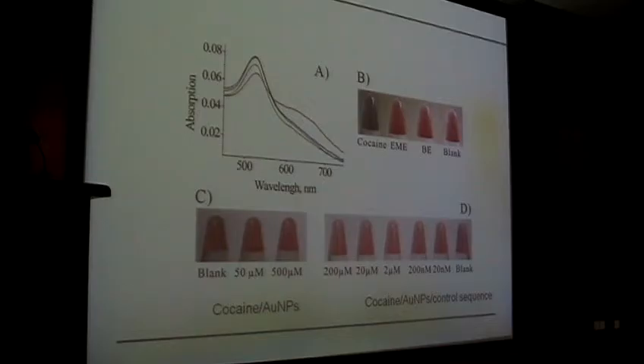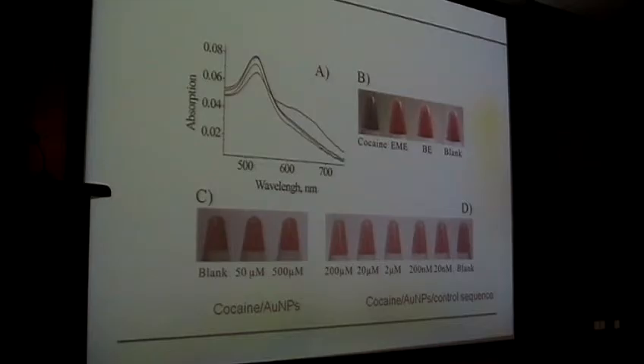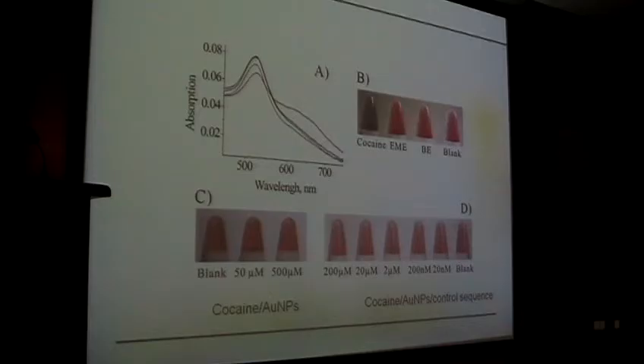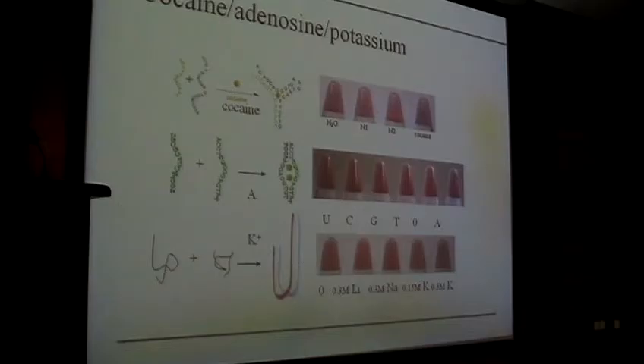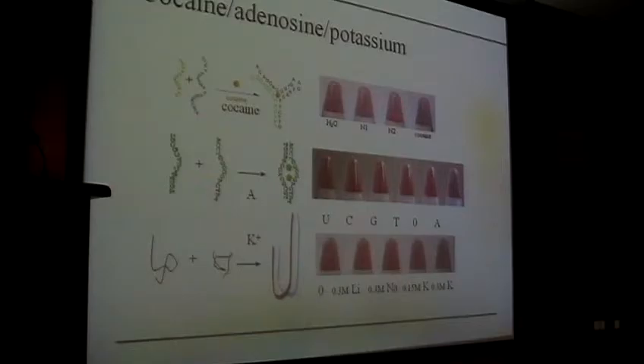The data confirm that the cocaine detection is specific — two similar molecules that cannot bind to the aptamer remain red. We can also detect micromolar cocaine in solution. This method is also applicable to adenosine and potassium. Most importantly, the kinetics are very fast — all reactions can be finished within five minutes. So this is truly a mix-and-detect assay.